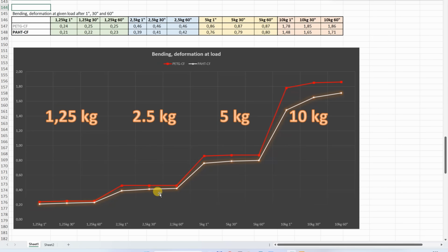First of all, we can see less deformation of the PAHT-CF compared to the PETG-CF. But what I don't like here is this. Well, under 5 kilograms it is not so noticeable, but on 10 kilograms we can clearly see that this is far from being horizontal. This means that this nylon doesn't really like higher constant loads.